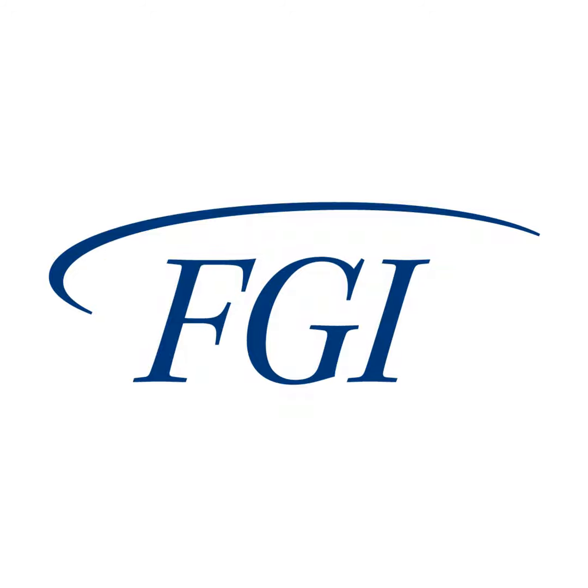I can go there. Reduction factor again. So I've presented you what's in the ISO method. GeoMat will have a reduction factor of typically 1.1 to 1.6. Biplanar GeoNet can be typically 1.3. You see also the difference in duration and normal loads, by the way, and all the numbers are going to be affected by this consideration, and temperature. Triplanar is typically lower, 1.1, box type 1.1.